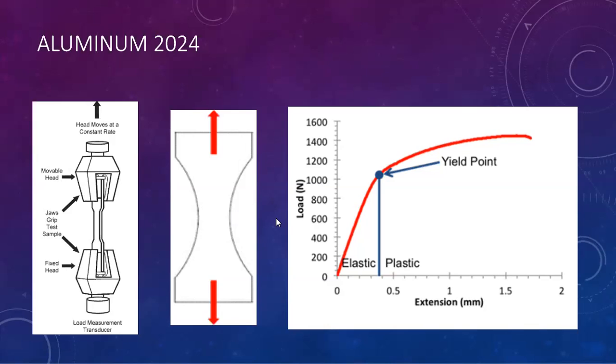So we could take scans with our laser beforehand, see how much second harmonic generation was produced, pull it, stress it mechanically, and then test it afterwards and see if there was a change in the way that our SHG responded.